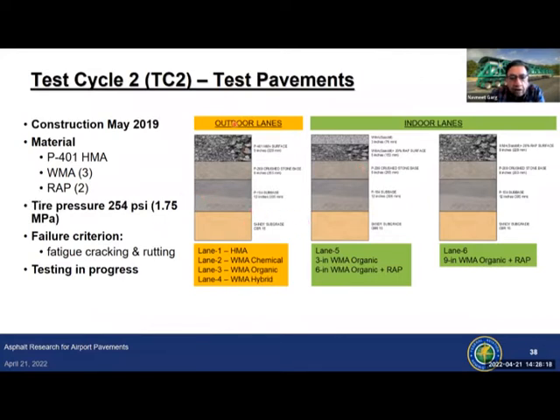On the outdoor lanes, we had a control lane that was P401 hot mix asphalt. And then we had 3 lanes with warm mix asphalt, and the binder grade was PG76-22 in all those lanes. Of the 2 indoor lanes, lane 6 had 9 inches of warm mix with 20% RAP included. And on lane 5, the top 3 inches was just warm mix asphalt. The bottom 6 inches had warm mix and 20% RAP included.